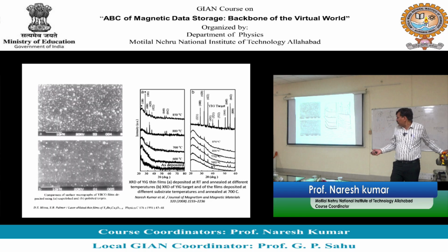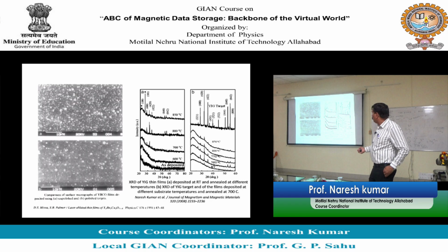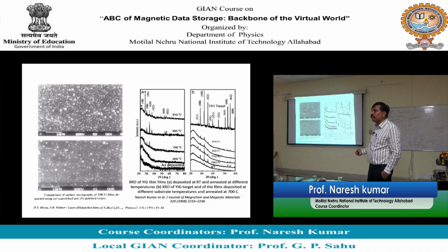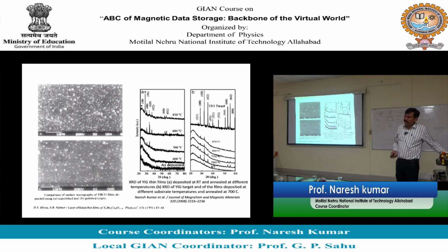Here I am just showing you one effect of temperature. See, film is grown at room temperature and then gradually annealed at higher temperature. The film is polycrystalline. It is grown on quartz substrate. But if the temperature is raised, you have some diffusion coming from the substrate. So impurity is getting in, and that can also be there.